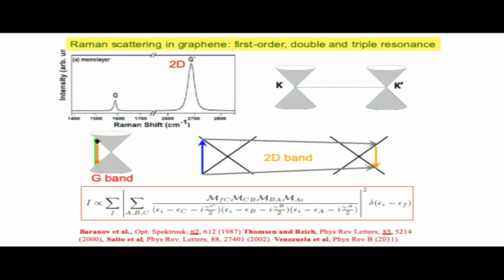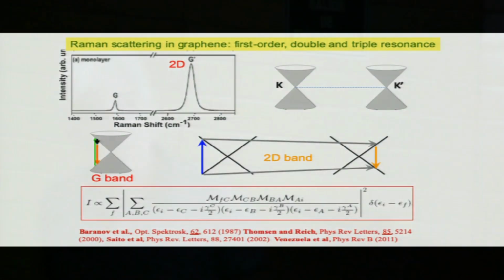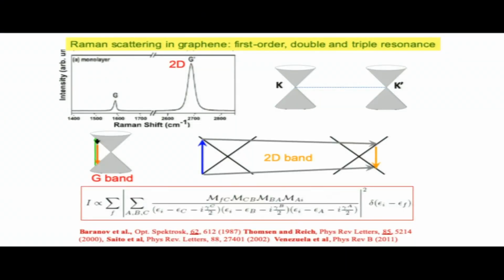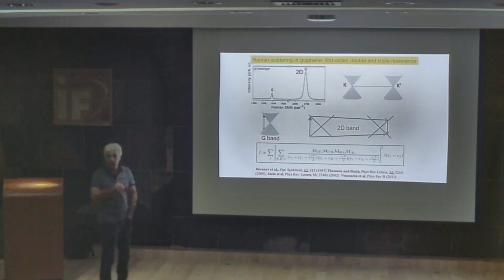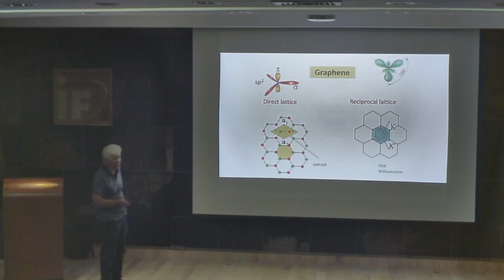Okay, now I will talk about Raman scattering in graphene. Raman spectrum in graphene, this is a good qualitative sample of graphene. We have two peaks. This we call the G peak, and this we call the 2D peak. The G peak is very easy to understand from this view graph here, because in the case of graphene, we can understand this honeycomb structure as two lattices, one formed by the red atoms and the other one by the green atoms. They are not equivalent because there is no translational symmetry that brings one into another.